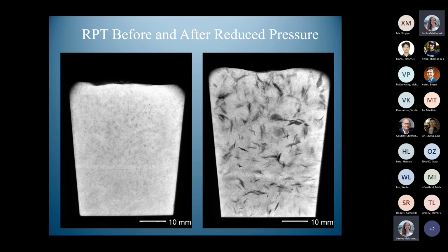When you look at some of these, this crack here, it's got a right angle and here's other kinks. This is exactly like the cracks we see. They never really straighten out, but they are serious as defects now. And so if we take, for instance, a machine, a tensile test piece out of here, it will almost fall into 2 pieces by itself. Its properties will be fantastically low.